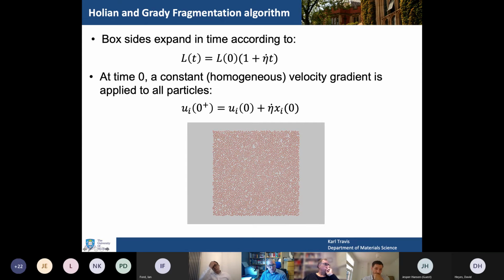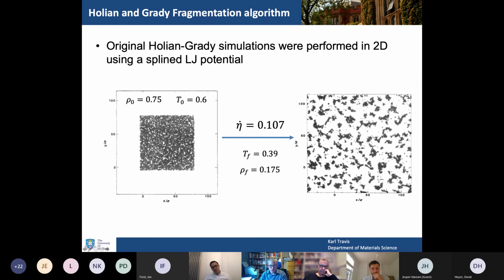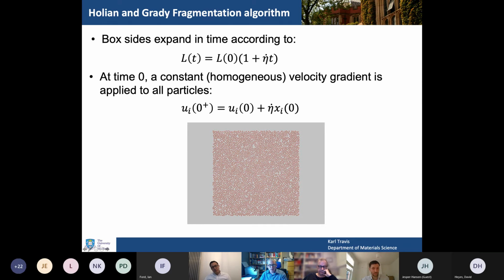And I said that you had to augment the velocities at time 0, so you take the thermal components of velocities and you add on this contribution here that accounts for the fact that it's expanding. So you do that at time 0. It's reminiscent of the way we used to do planar Couette flow before SLLOD and DOLLS came along. You did it through the periodic boundary conditions, the so-called Lees-Edwards sliding brick periodic boundary conditions, and you just waited for the flow to develop. The DOLLS tensor, on the other hand, does it through the equations of motion,